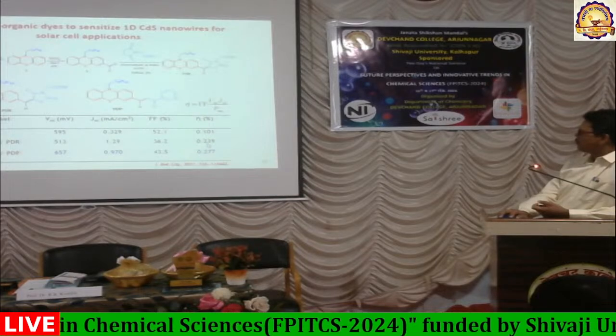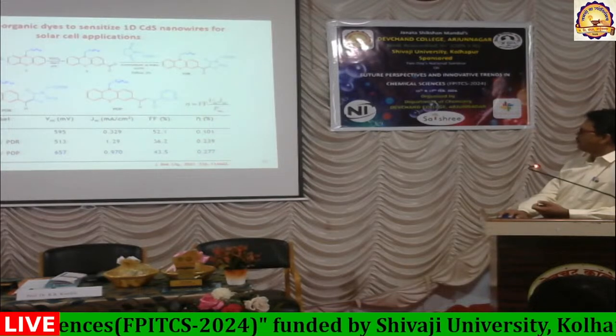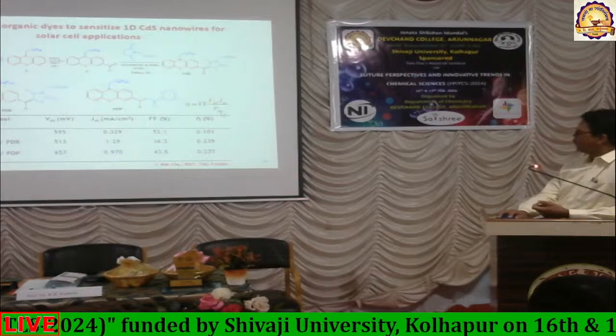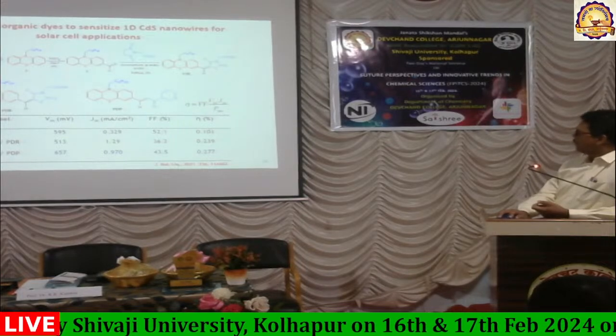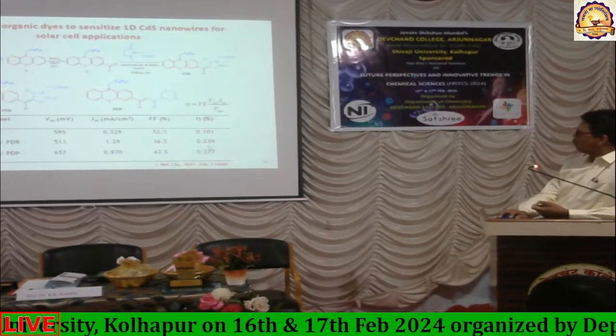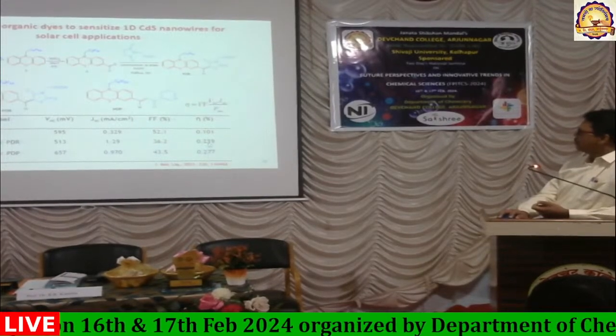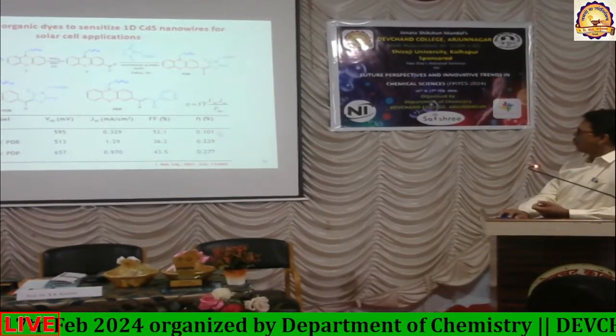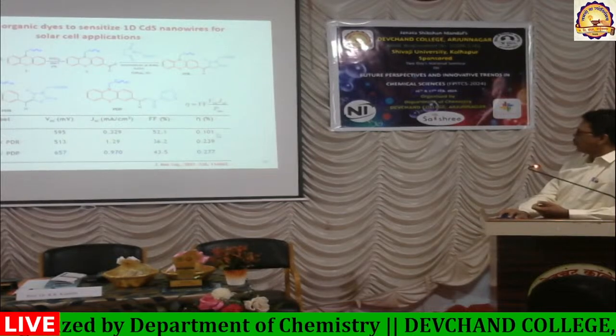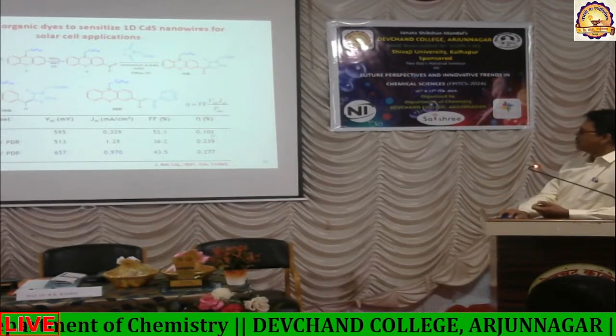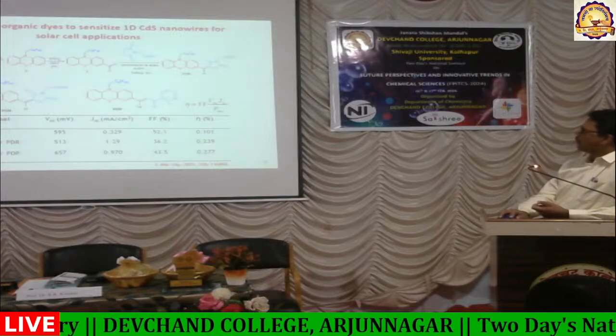When we introduced our dye, the efficiency was found, because efficiency is nothing but the ratio of power output to power input. We saw an enhanced power output, almost 2 times enhanced in the presence of these dye molecules, from 0.101 to almost double the efficiency with these 2 dye molecules.